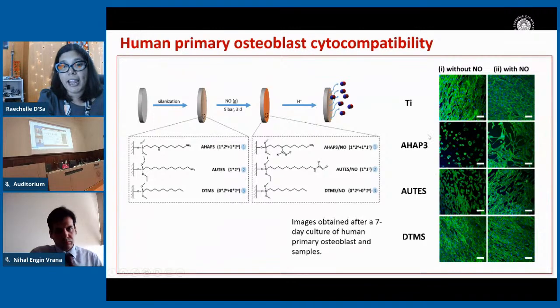Now, on our 2 silanized surfaces where they have the capability of tethering nitric oxide, what we find is that our AHAP surface, which has the higher amount of nitric oxide and the slightly better bactericidal effect, the osteoblasts don't like the silane surface, but on the nitric oxide surfaces, the cells do grow a little bit better, although they've got slightly shrunken morphology.